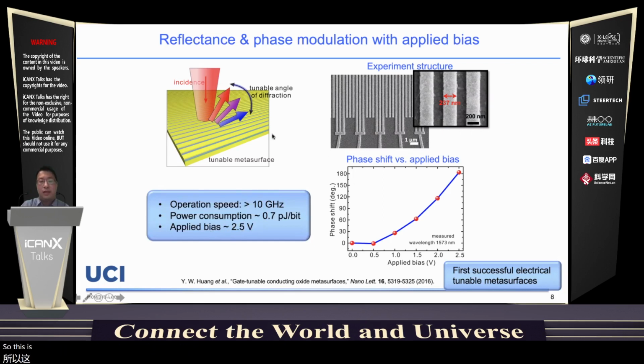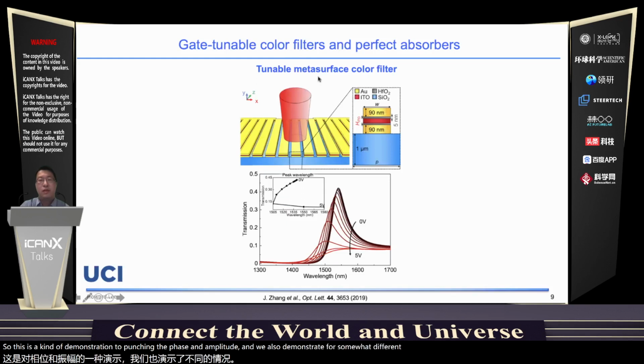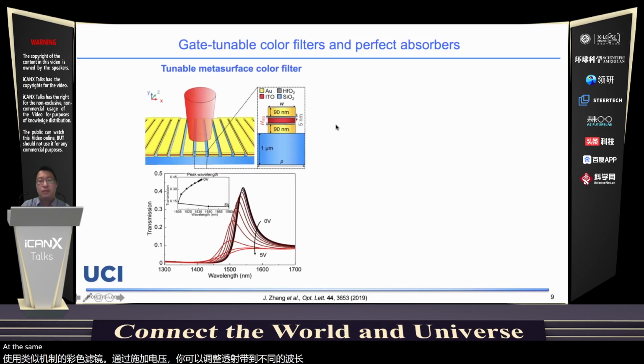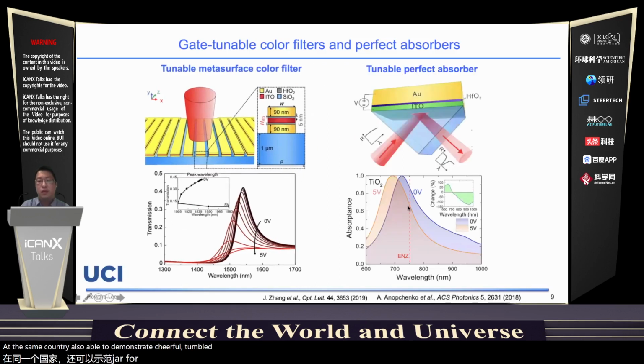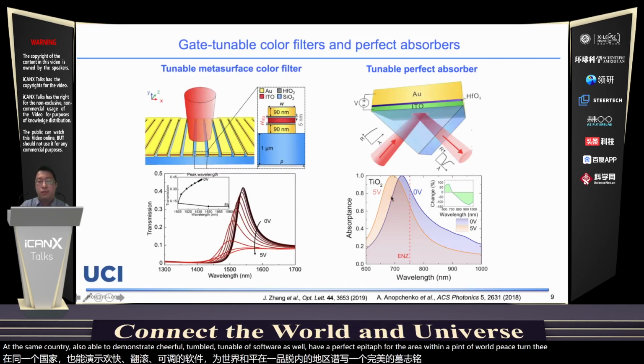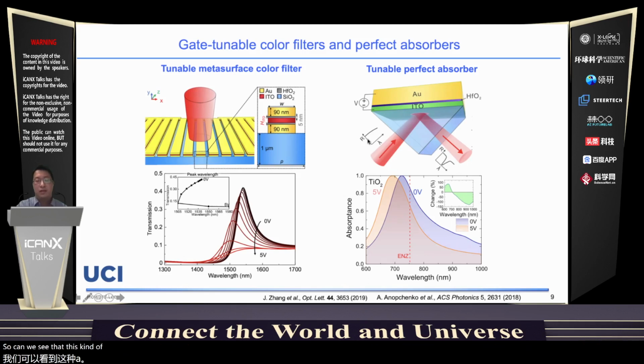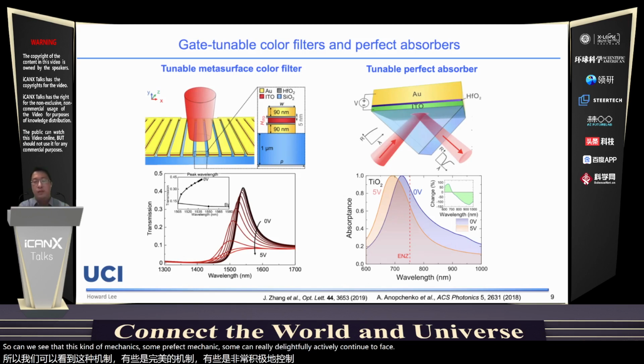So this is a demonstration of controlling the phase and amplitude, and we also demonstrate, for example, in a different structure, that we can make a tunable color filter using a similar mechanism by applying voltage. You can tune the transmission band to a different wavelength. We're also able to demonstrate a tunable absorber. We have a perfect absorber here, and we can apply voltage to tune its wavelength of operation. So you can really see that this field effect mechanism can electrically and actively control the phase, amplitude, or even transmission and reflection of this kind of metasurface structure.